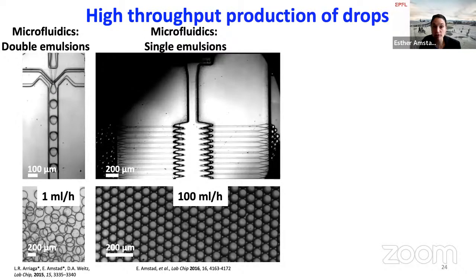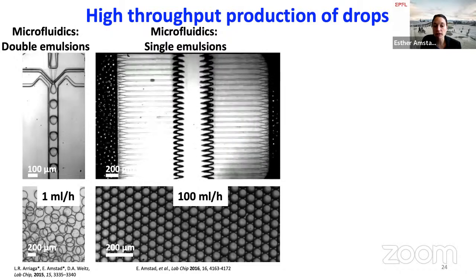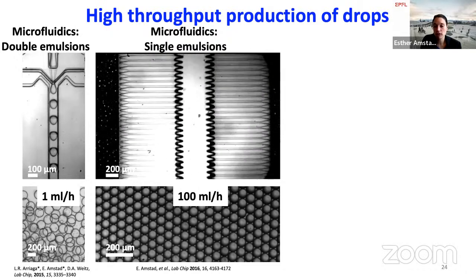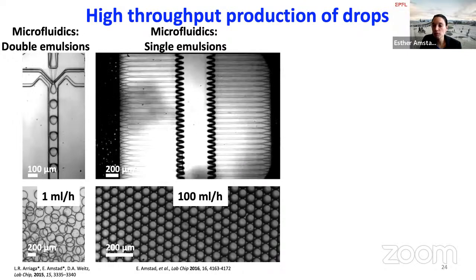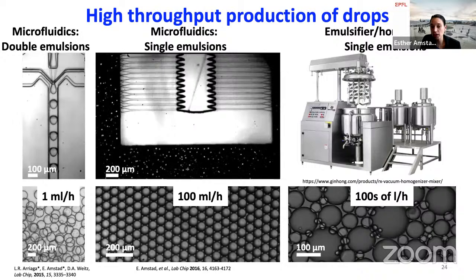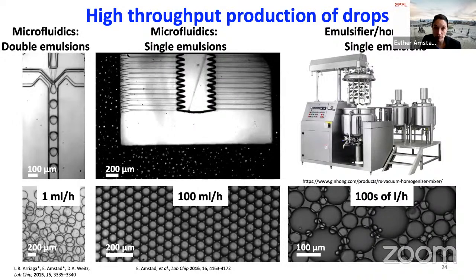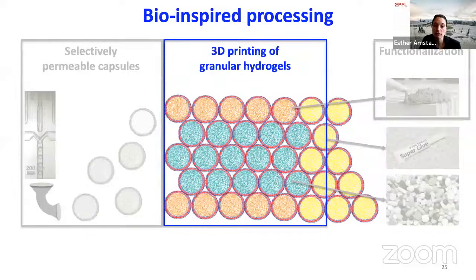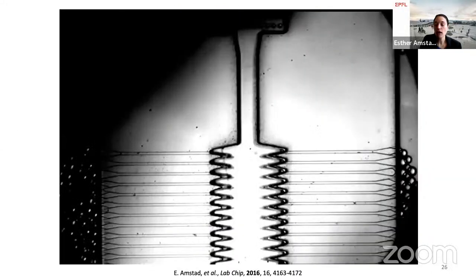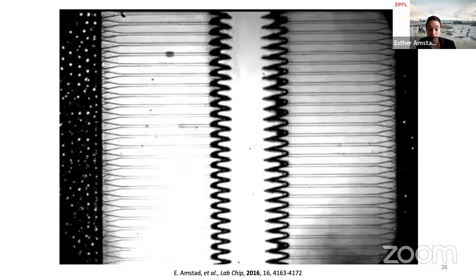If you in contrast can make capsules from single emulsions, well, you can easily scale up by a factor of 100 without compromising the control on the size. And if you don't care about the size, you can emulsify in bulk with bulk methods, and then you can easily produce even kilograms of these capsules per hour. So then scalability suddenly is really not an issue anymore. And that was a big advantage, and to me also a game changer in terms of using this technology for fabricating macroscopic soft materials. So that's what we did then. We started doing single emulsions using a device that I again developed as a postdoc in the lab of Dave Weitz. We call it the millipede device because it has about 1,000 nozzles.